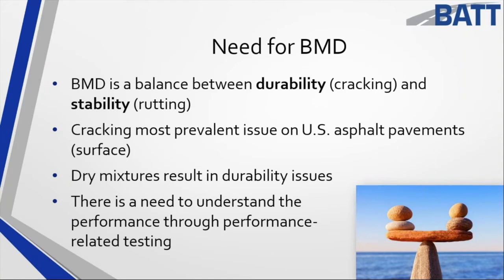The mix I'm using has about eight percent natural sand in it. When I added the asphalt, it does rut more — but rutting is not an issue for this application. If it only has 8,000 passes in a Hamburg test, I'm okay with that because this is not for an interstate level highway; it's for a secondary type highway. The cracking, though, went from the low 90s, pushing into the 200 level. That's where the aramid fiber comes in — to help you enhance that mixture way beyond what you could do with just asphalt and aggregate.